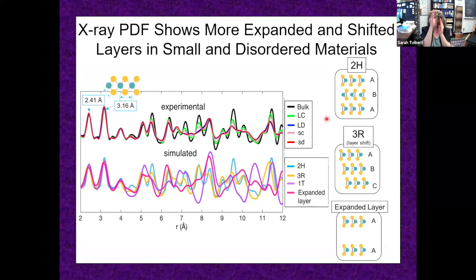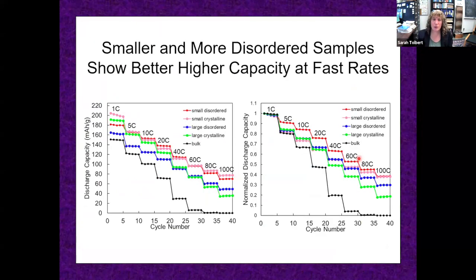That could make it hard to have a phase transition, but that doesn't do much else. The ones that are made at low temperature have sliding, but they also have expanding. So the layers are far apart. So disorder makes bigger pathways for lithium to move. Crystalline just makes it so that the crystal structure isn't so perfect.